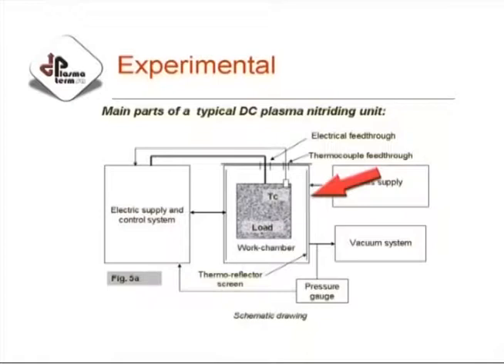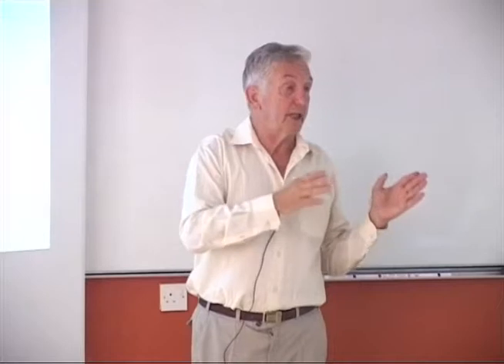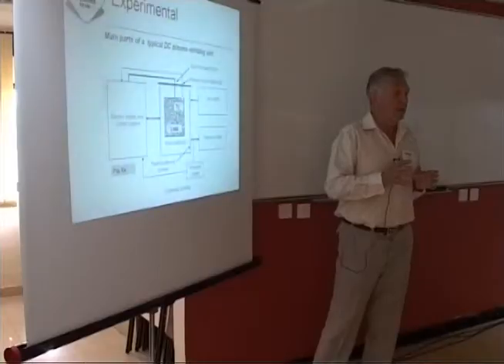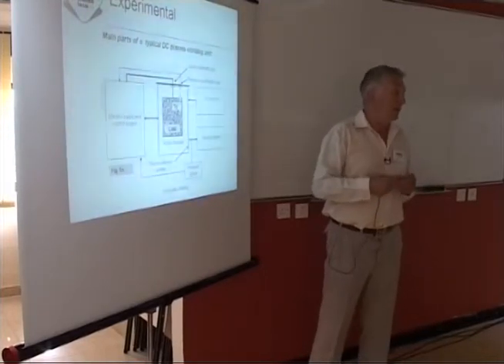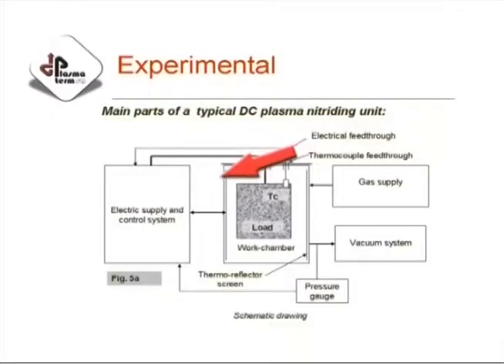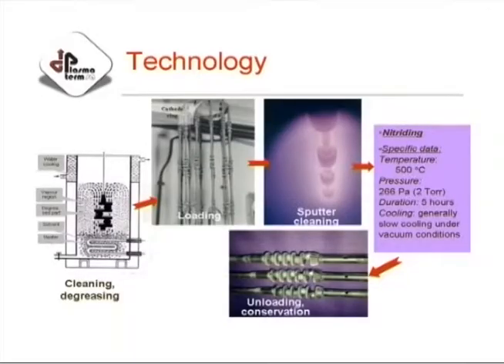It's the vacuum chamber, connected to a vacuum system and a pressure gauge. It has a specific gas supply, which is either a mixture of nitrogen and ammonia from bottles, or in our case, we use dissociated ammonia, and we add methane for hydrocarbon, and certainly an electric supply and control system. When we consider the technology, the whole technology is illustrated here. So first of all, we need cleaning and degreasing, which is extremely important for nitriding or nitrocarburizing.